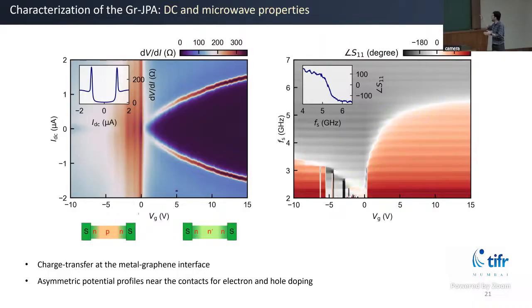So the resonance frequency is going up, which is correlated with the critical current, because as a function of gating, the critical current increases. So here the resonance frequency also is going up. So our resonator is tunable. You can change the resonance frequency with gating.